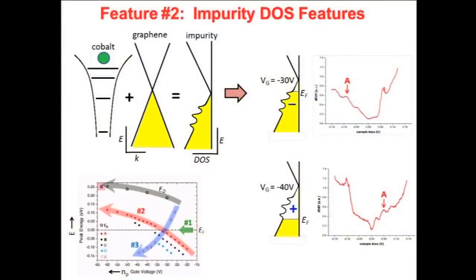And something that's kind of nice, something that's kind of new, I think, is that we can change the energy level of those defect states with the back gate. So we can gate our atom, we can gate the surface, and we can move those defect states up and down in energy. And the reason that's significant is because that allows us to fill or deplete those defect states with charge. So here, for example, I'm showing you a scenario where we've gated the sample at a gate such that these defect states are below the Fermi energy, and I have a negative sign there to indicate that they're filled with charge, negative charge, because they're below the Fermi energy.